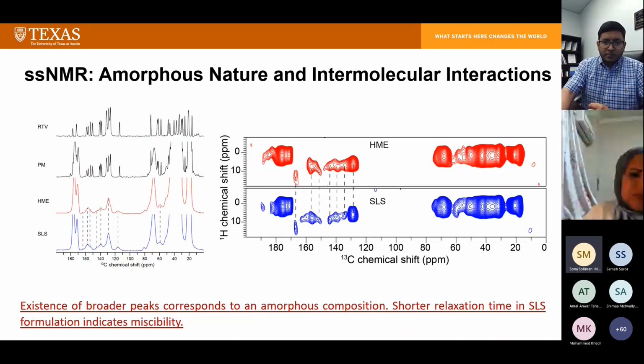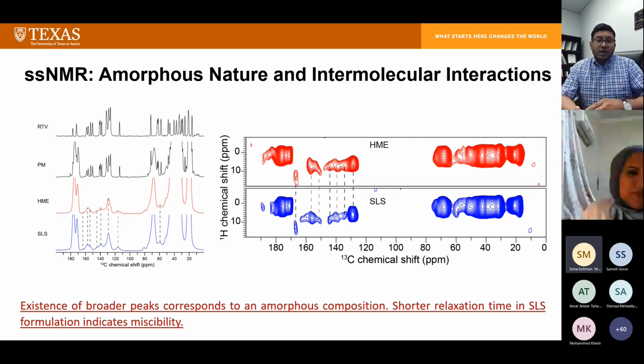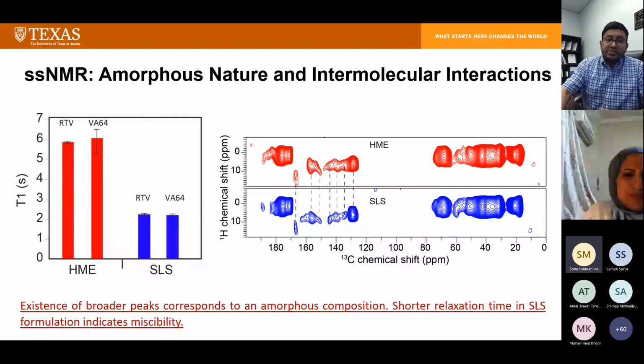So these are physicochemical characterizations, which show that after the single-step process optimization, the highly crystalline ritonavir converted to its amorphous form, and there was no evidence of crystallinity. We also did advanced characterization for the amorphous nature and intermolecular interactions analysis by 1D and 2D solid-state NMR analysis. What we found was that our drug was present in amorphous form after the SLS process, and there was a higher degree of mobility in our 3D printed dosage forms that was reflected by the shorter relaxation time.